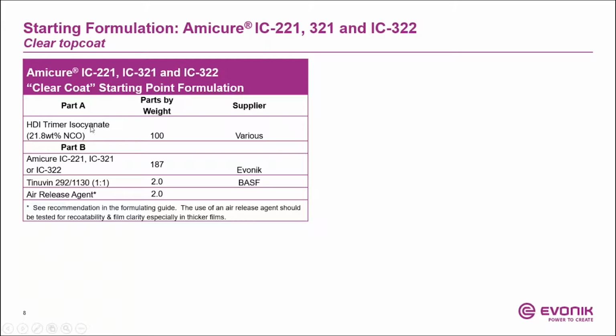Part A is a standard polyisocyanate HDI trimer. Part B, you can use either of these three curing agents by itself or as a blend. There's an optional ingredient of a UV stabilizer, and an important ingredient is an air release agent, and we can recommend which air release agent works well in this formulation. These are almost 2-to-1 by weight, but in terms of by volume, it is a 2-to-1 mix ratio.